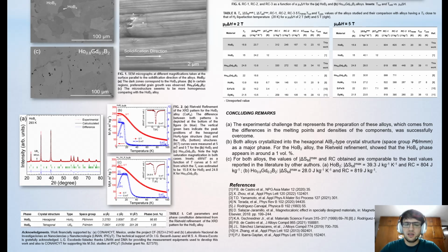In figures 2b and c, we show the magnetization curves measured at 5 Tesla and 5 millitesla. In both cases, for both alloys, we see that we have a high saturation magnetization, which could influence positively in the material's magnetocaloric response. Additionally, the absence of anomalies in the 5 millitesla curves indicate that we have no presence of other magnetic phases. The insets in both figures display the derivative of the magnetization as a function of temperature. The Curie temperature for the holmium diboride was estimated to be 16 Kelvin, while for the gadolinium doped alloy it was estimated to be 25 Kelvin, temperatures that are close to the hydrogen liquefaction point.